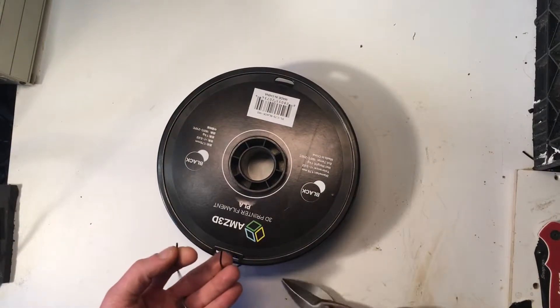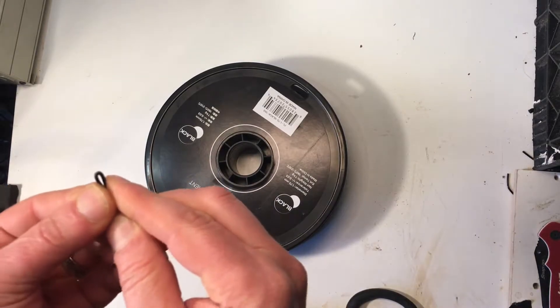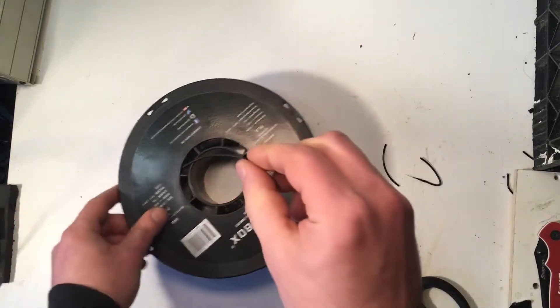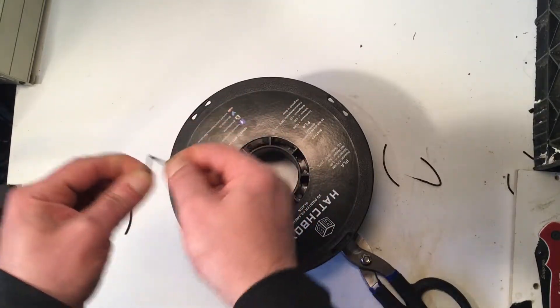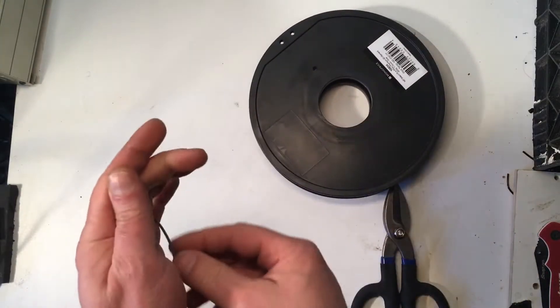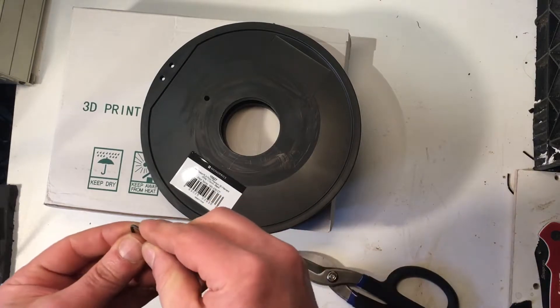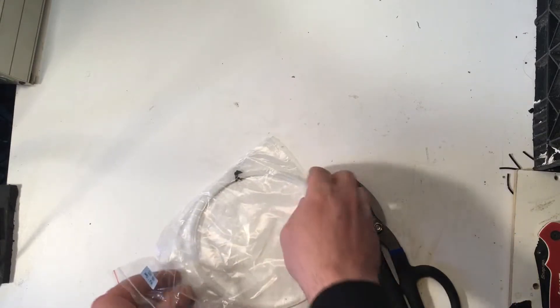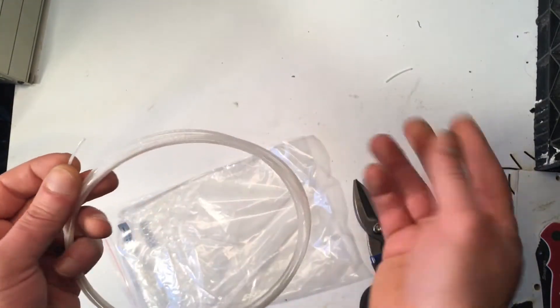This filament is a couple months old — I pull off a piece and give it a bend test. It's pretty good; no snapping, I have to bend it back and forth a couple of times before it breaks — looks printable. Same thing with this Hatchbox filament, about six months old — even better shape, probably because Hatchbox filament is slightly better than the generic stuff. The gray Monoprice PLA Plus also seemed nice and pliable. I tried about seven different spools and most seem pretty good. Then I found a spool of starter filament sealed up in a bag — that's been held at much lower humidity — and that's just falling apart in my hands.